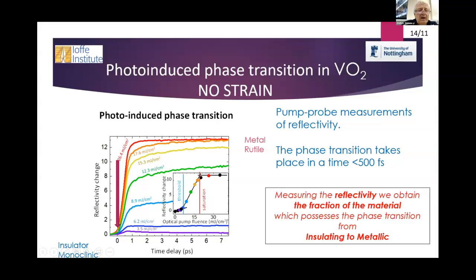The important thing is that phase transition is known to happen at very short times, less than 500 femtoseconds, for both the insulator-to-metallic and structural phase transition. Then there is a stage called the metastable state, and what happens in this metastable state is not really clear nowadays because it depends on a lot of parameters. The main thing is that phase transition happens at a very short time, and what happens next, people are still asking questions about this.